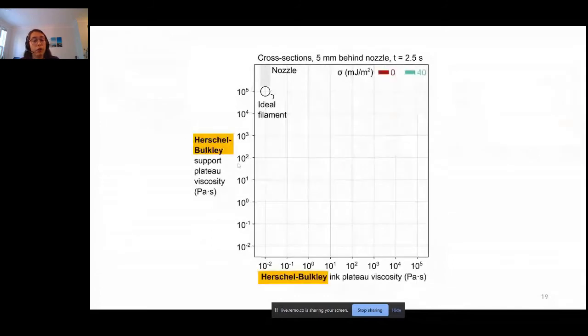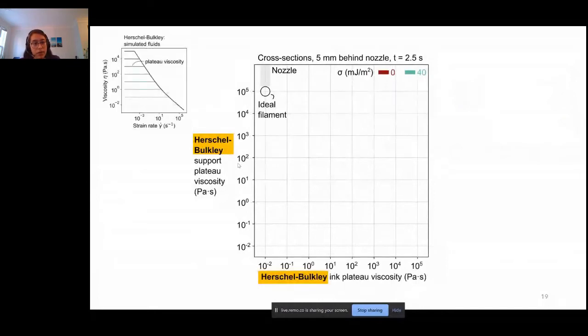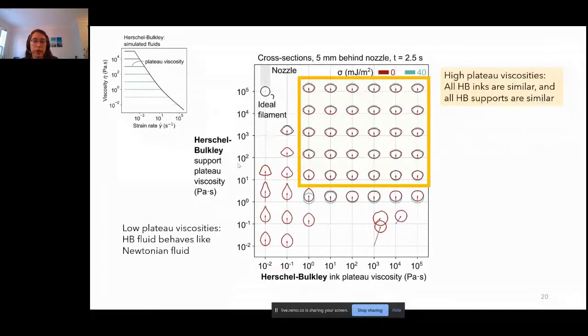Now let's look at Herschel-Bulkley fluids. So here we're going to have a constant plateau viscosity up until yield stress, at which point the viscosity will drop off towards shear thinning behavior. So here what you can see is if you go to a high plateau viscosity for both the ink and the support, beyond a certain point, all of the cross-sections are the same. So all of these Herschel-Bulkley inks behave similarly, and all the Herschel-Bulkley supports behave similarly. And remember, the way that we set these viscosity curves, the viscosity above yield is the same for all of these.